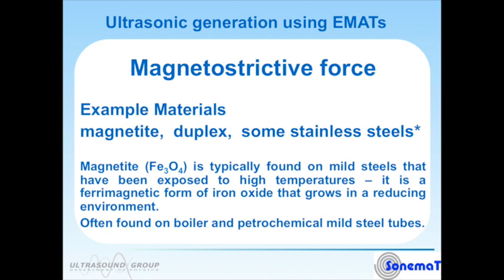Magnetite is a high temperature iron oxide that's typically found on mild steels that have been exposed to high temperatures. It's actually a ferrimagnetic form of iron oxide. Pipework that's been used at high temperatures, quite often under insulation, develops an oxide scale. This is often found on boiler tubes or petrochemical steel tubes.